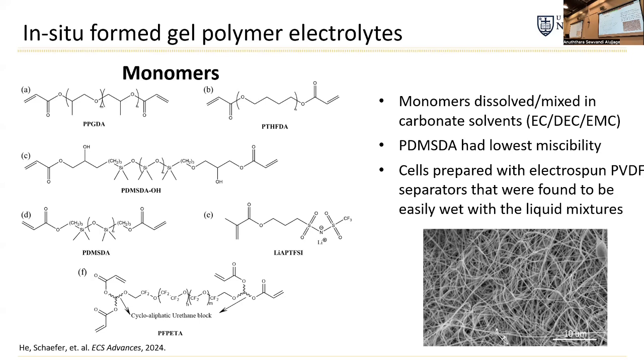So we found that actually most of these are soluble in carbonate mixtures. We looked at an EC, DEC, EMC mixture. The PPGDA, the poly-THFDA, and the perfluorinated polyether were very, very highly soluble. We went all the way up to 50% polymer and they were soluble. But PDMS has limited solubility or miscibility. And then we also found separator chemistry to be a big challenge.